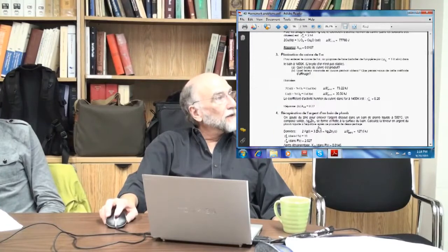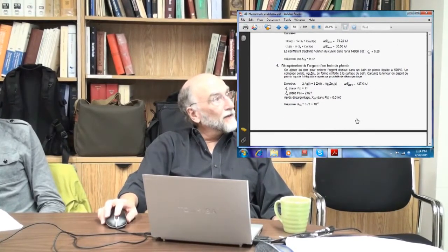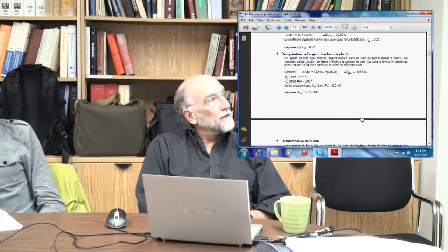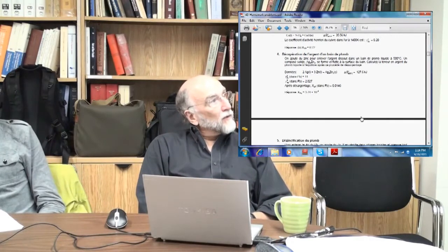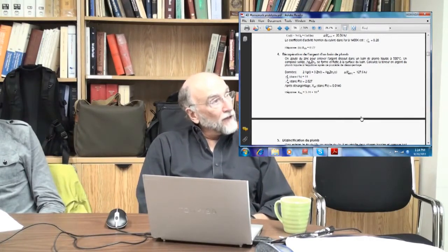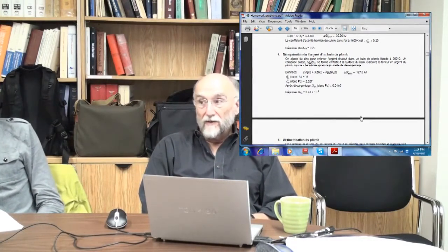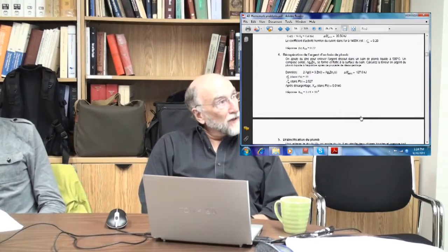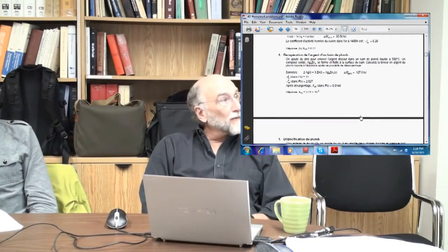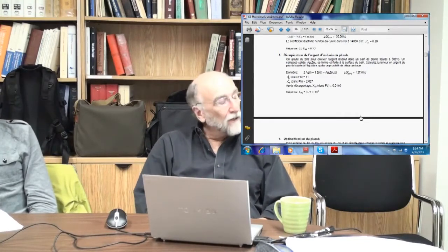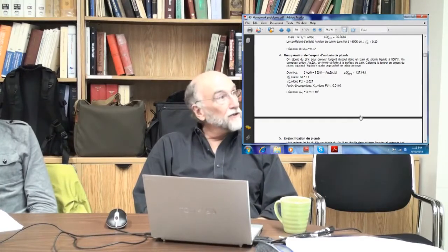Number 4, recuperation of silver from a lead bath. When you make lead, lead ore contains silver with it. Lead sulfide contains silver sulfide. So when you make lead liquid, in a carbothermic pyrometallurgical process, you end up with quite a bit of contamination with silver because it gets reduced too.